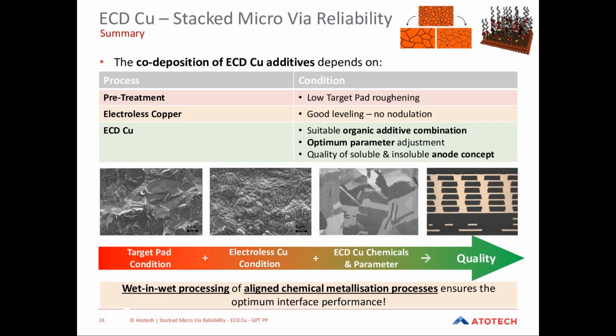One reason is that the anode film, which partially continuously gets dissolved in the plating solution, this anode film increases the contamination of the electrolytic plating process over time. And here we found a slight tendency, depending on the copper anode quality of the anodes. Here we found a slight tendency also that insoluble anode systems are much more stable over months and years in this regard, not creating this dissolving anode film in the electrolyte.